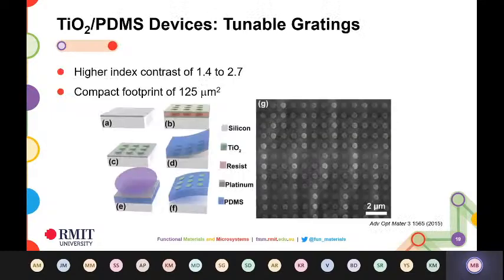So, for instance, we used the same transfer process, and we used titanium dioxide in this particular case to create tunable gratings. If you look at titanium dioxide on PDMS, there's a very high refractive index contrast of 1.4 versus 2.7. So this was a nice, very quick demonstration to show, one, that you can use the transfer process to create these kinds of grating devices using titanium dioxide. And two, you can actually use mechanical strain to tune those gratings.